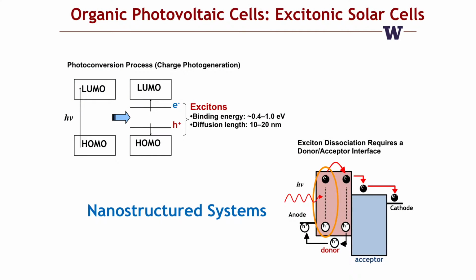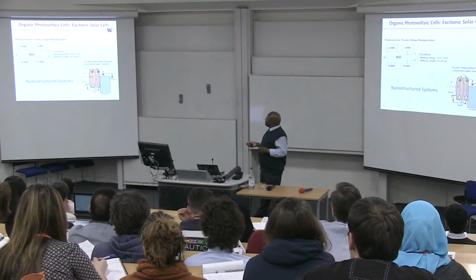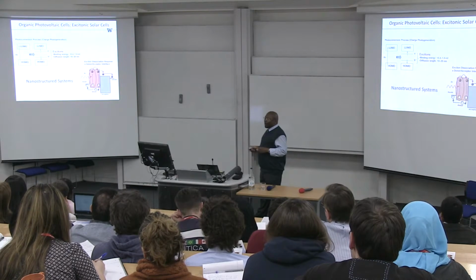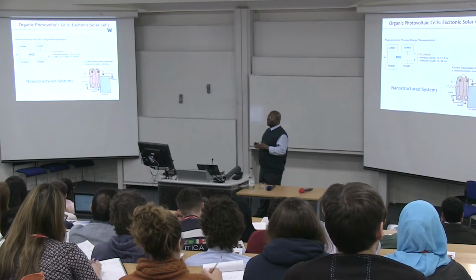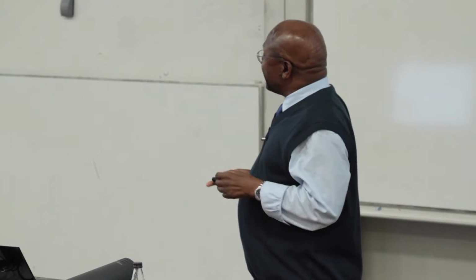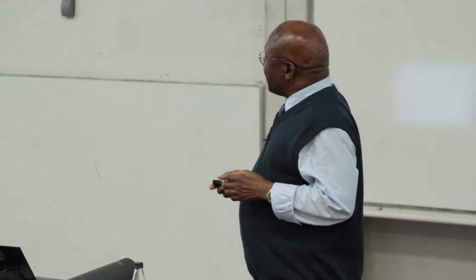And in fact, when you shine light on an organic semiconductor, whether in the device or in a film, what you create with the light, with the photons absorbed, are excitons, electron-hole pairs that are bound together very strongly with binding energies that are quite large, which you have to find a way, within the lifetime of the excitons, to break up and collect the charges as current.